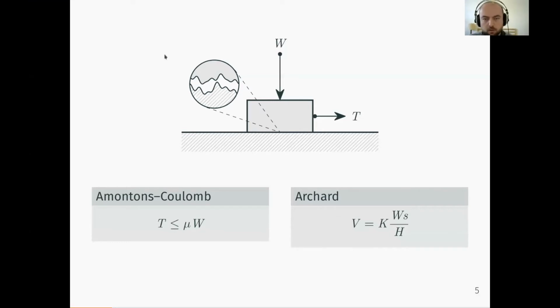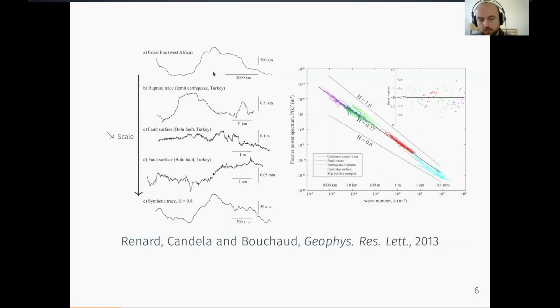And so we need to be able to describe properties of roughness. You might know that roughness has a self-affine characteristic in natural surfaces. This work by François Renard and co-workers measured geological fault surfaces at the kilometer scale, at the meter scale, at the centimeter scale. What they found was that as you zoom in on scales, you still find more and more roughness. They also compiled power spectral density for those roughness measurements and put it in this plot, where they have measurements of different roughnesses at different scales. They have a nice parallel scaling over tens of orders of magnitude, which means that roughness is basically a scale-free occurrence in nature. There isn't a particular scale that determines the roughness of a surface.